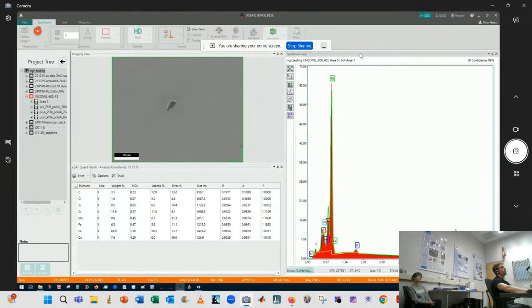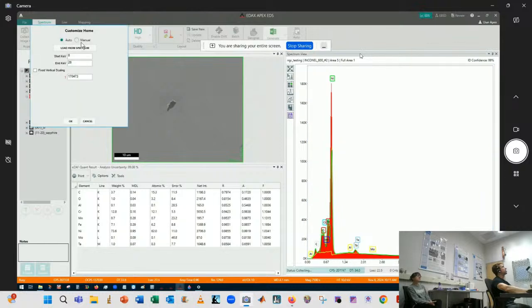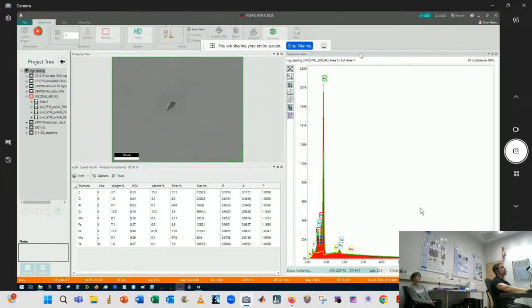Okay. So anyways, this is what we have. We see a big nickel peak, which we would expect. We also see chromium like we would expect. It looks like there's also maybe some other elements as well. We see a little carbon, which is surface crud. I can actually change this here so we can see further back. Okay. Yeah, so then there's the other nickel peak. So when this is done, we can remove this. So basically, it looks like we've got nickel, we've got some chromium.